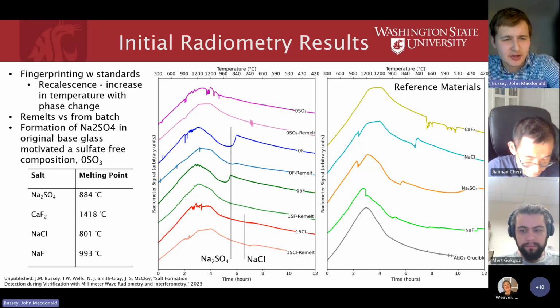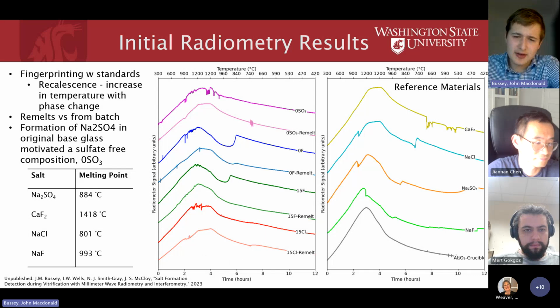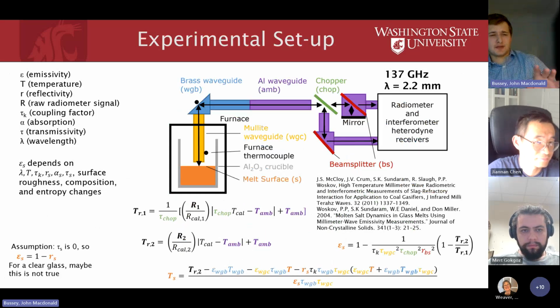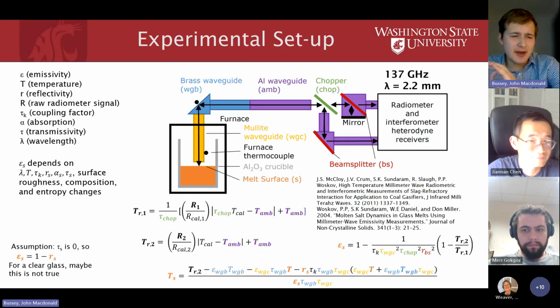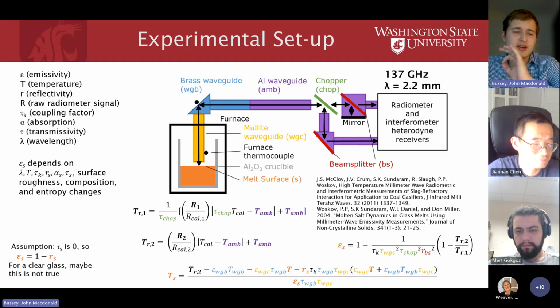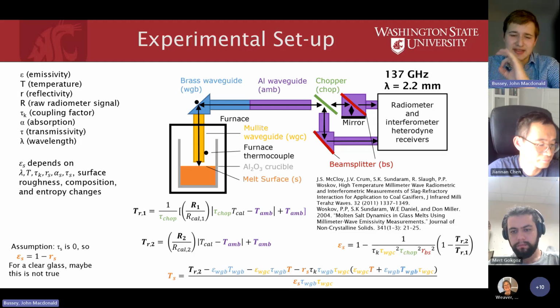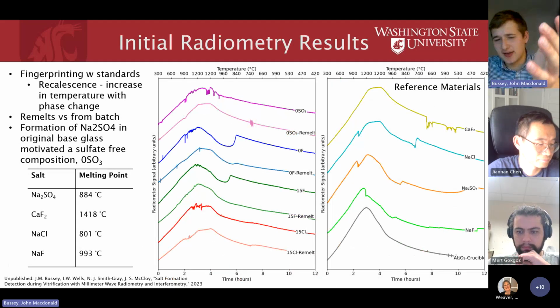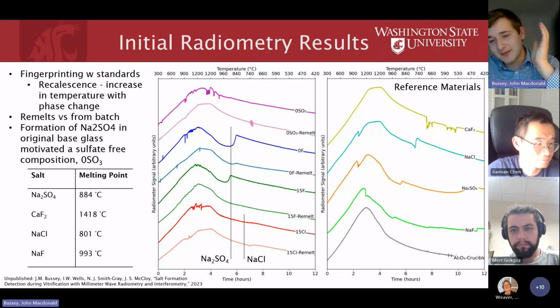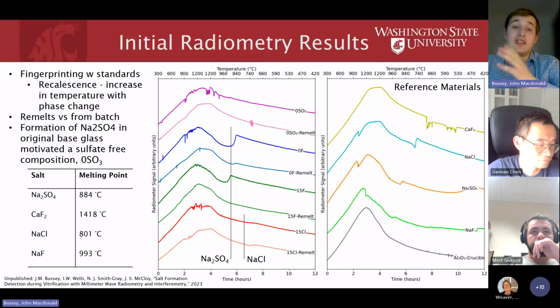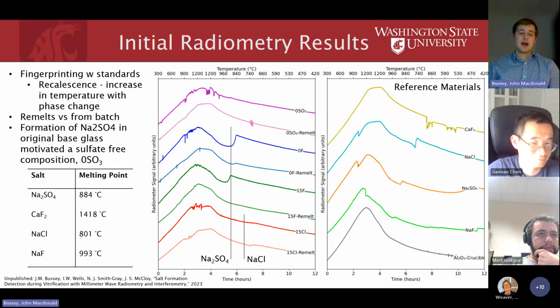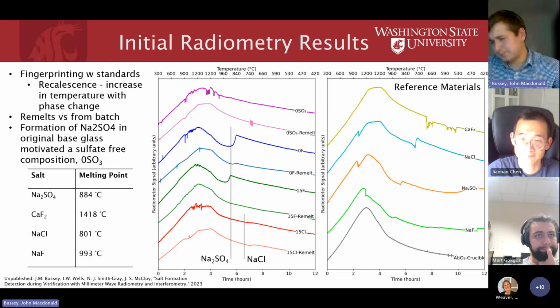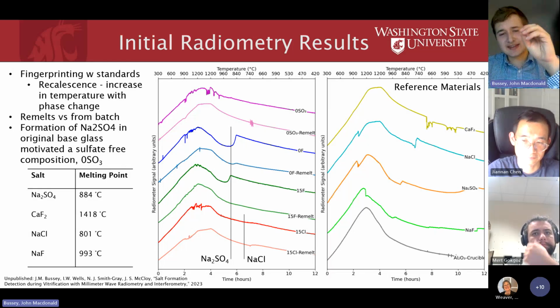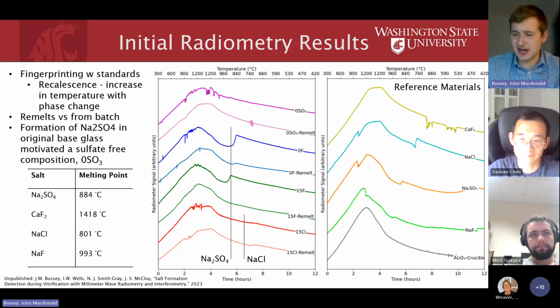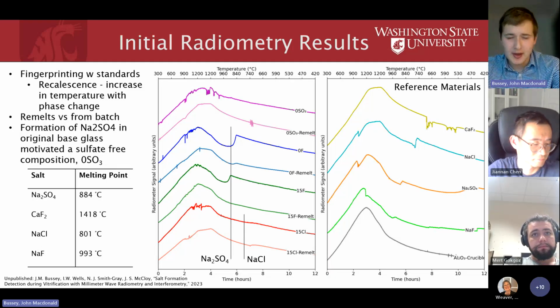This recalescence temperature is, so back to this last slide for just a minute. Emissivity depends on a variety of factors, including the thermodynamics of the sample. I don't know why I backed up 2 slides to show you that, and I didn't need to. But the emissivity is related to the thermodynamics of the sample. And so when you have a phase change, when you have a release of heat, we can detect that, and so even this emissivity change, we can tie this with the radiometer.